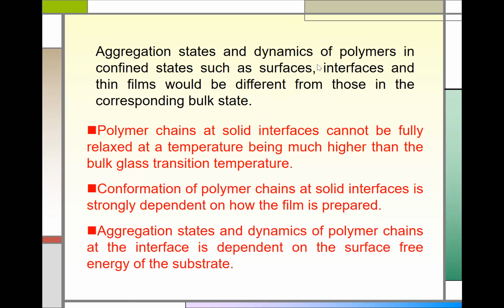Again, polymers in confined states such as surface and interface. I skipped surface, but I just concentrated on looking at interfaces, and they are totally different from those in the bulk states, the internal region. And polymer chains at the solid interface cannot be fully relaxed at temperatures much higher than the bulk glass transition temperature. And the conformation of polymer chains at the solid interface is strongly dependent on how the film is prepared. So this is very important.